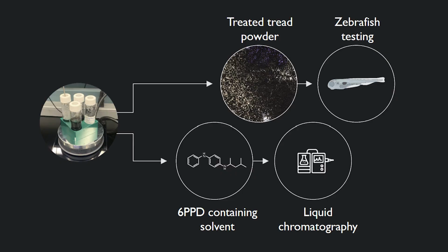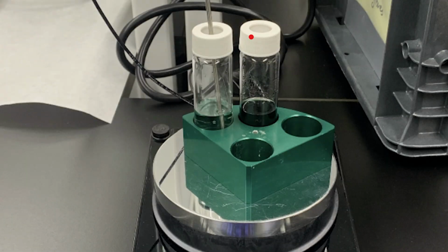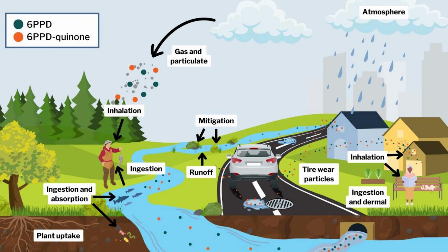We also found that concentrations even as low as 3.2 parts per billion of 6-PPD, which is comparable to the concentration of stormwater runoff from cities, cause underdevelopment and lack of pigmentation in these embryonic zebrafish. Using solvent extraction techniques, we were able to extract 6-PPD from pulverized crumb rubber. This allows us to study not just the presence of the chemical, but its potency, pathways, and how it might be removed, cleaning the dangerous compounds from recycled tire material before they hit playgrounds and parks.